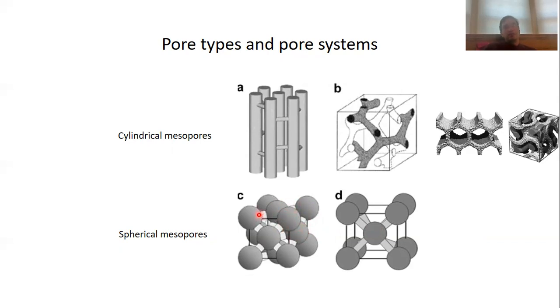Rather, they interpenetrate to some extent, and that interconnects these spherical mesopores via bottlenecks, and the bottlenecks themselves can have several nanometers in pore size. So that leads to overall three-dimensional pore systems.